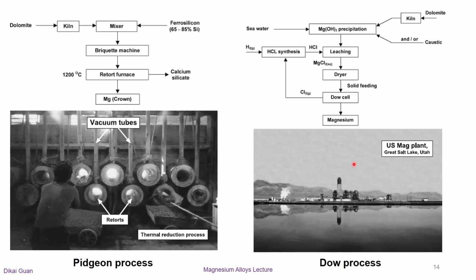The right part of this slide shows magnesium production based on the Dow process and the Mag plant using the Dow process to produce magnesium in Great Salt Lake, Utah. A magnesium chloride solution is produced by adding hydrochloric acid to magnesium hydroxide extracted from the seawater precipitate. The solution is then condensed by heating and dehydrated in order to minimize the formation of magnesium oxide due to the decomposition of magnesium chloride. Dehydration is terminated at the stage where one molecule of crystal water remains. The byproduct chlorine from the electrolytic cells is recycled into hydrochloric acid for use at the front end of the process.